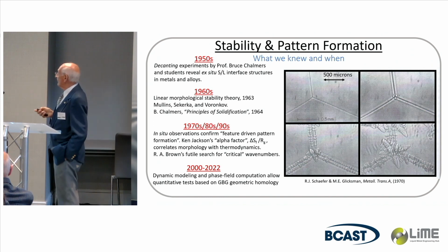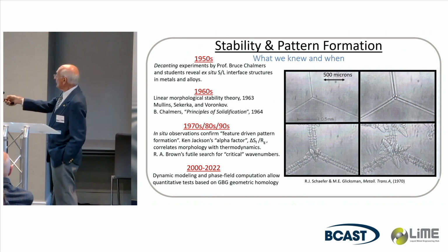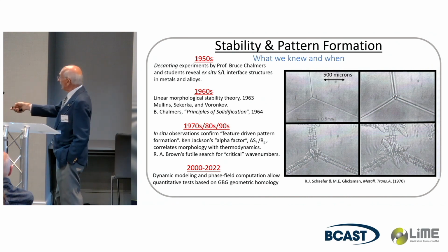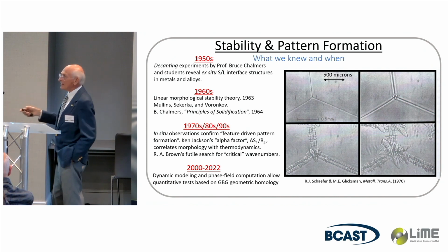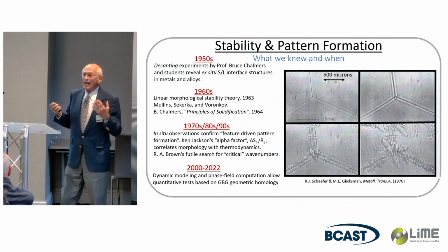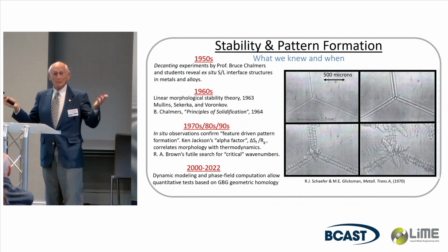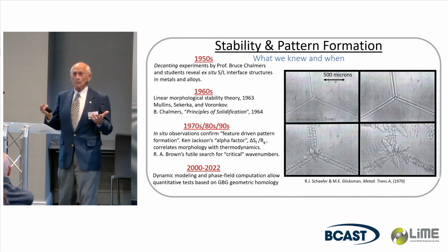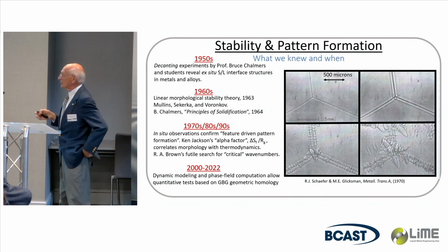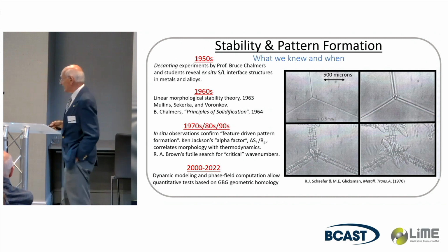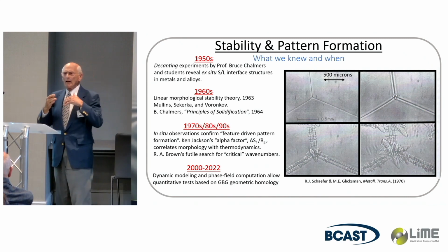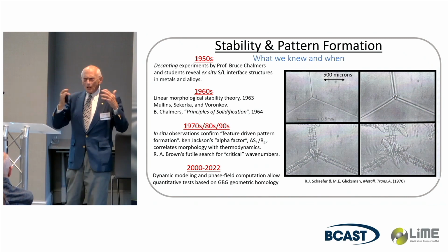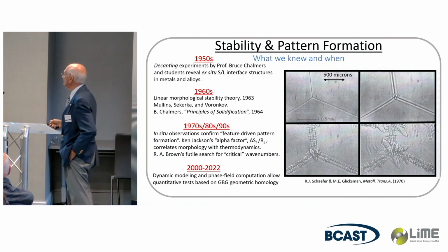Another important development was by one of Chalmers' students, Ken Jackson, who passed rather recently. His so-called alpha factor, which is the ratio of the entropy of fusion to the gas constant, he proved correlates morphology and thermodynamics. That if that alpha factor is 2 or less, that's typical of the metals, you get rather metallic solidification, and as it goes up to numbers above 2, up to maybe 50, 60, you get needle-like and spherulites, rather non-metallic solidification.